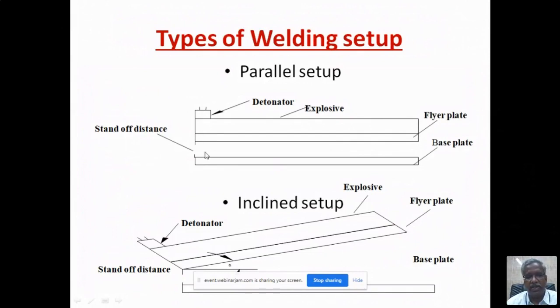And another thing is you have to keep some distance between the bottom plate and the flyer plate. So that distance is known as the standoff distance. The standoff distance again has a relationship with the flyer plate thickness. The thickness of the flyer plate will decide how much standoff distance you have to keep. Whether it is 0.6 or 1 or 2 times the flyer thickness, it depends on the material. What is the flyer material and what is the explosive you are using. These data are established for many materials, many combinations. It has been established.